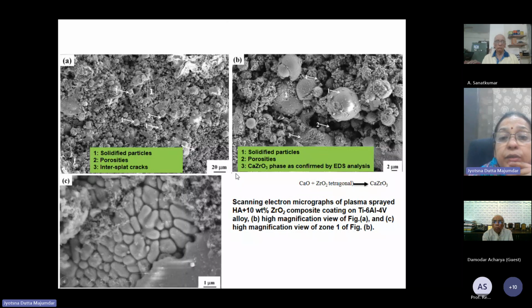In the other case, when we did the zirconia coating, the zirconia particle size was very small. So we find very fine particles of zirconia in addition to hydroxyapatite phases on the surface. There are also some porosities present in the microstructure.